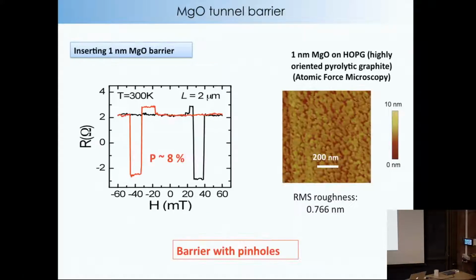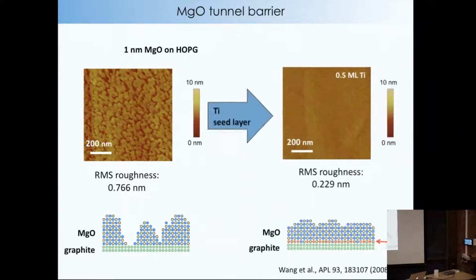Okay. So we tried to do that at first, and we had some success. So we put in a MgO tunnel barrier, or we put in a barrier, we just grew it, and we went from 1% to 8%. And so we were happy. I mean, our signals are getting bigger, and everything's nice. But we noticed that it wasn't actually a tunnel barrier. We looked at the temperature dependence, we looked at the IV curves. It looked like an ohmic contact, except higher resistance values. And when we looked under AFM, we grew on graphite, and it was pretty rough. So we said, that's not good. So we developed a trick.